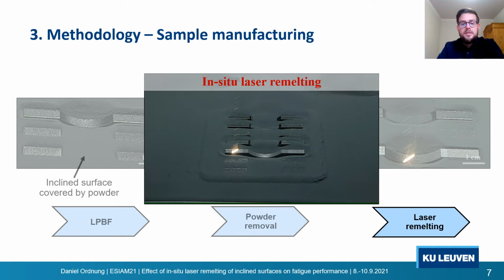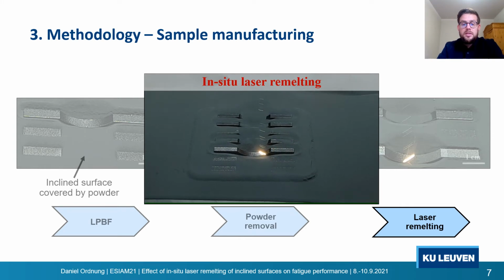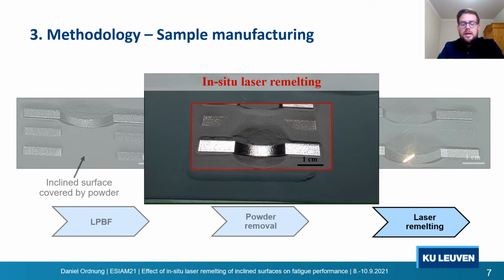In the video you can see the continuous wave laser starts to scan the inclined surface and repeats that several times until a shiny polished surface is reached. In this case, the surface was scanned 4 times and it ends up with a very shiny surface here to see in the picture.